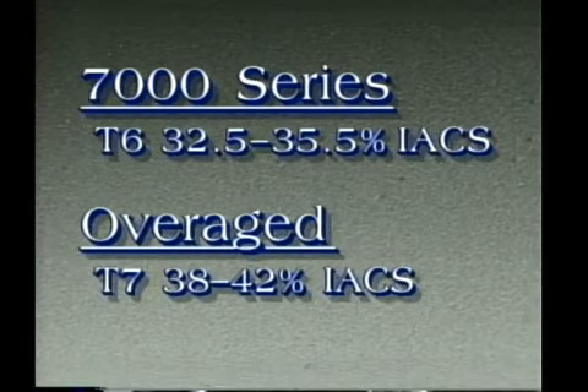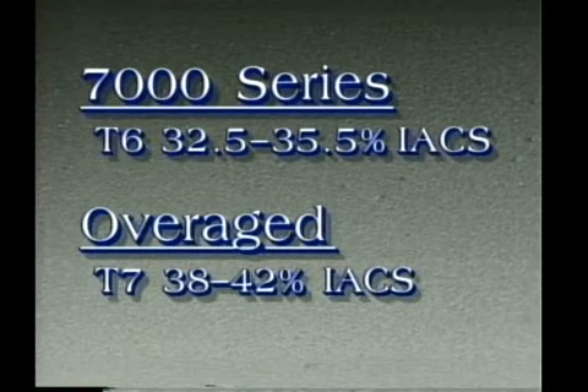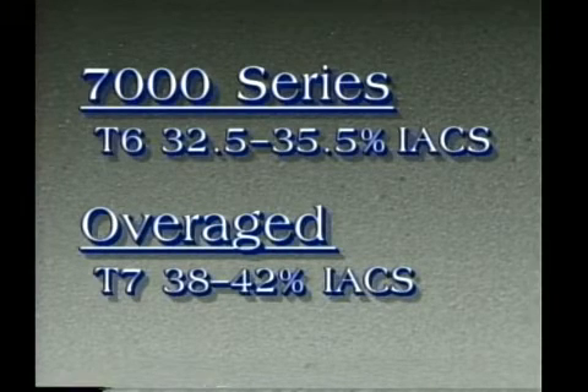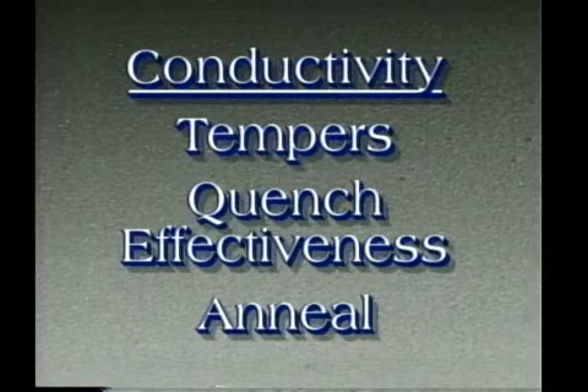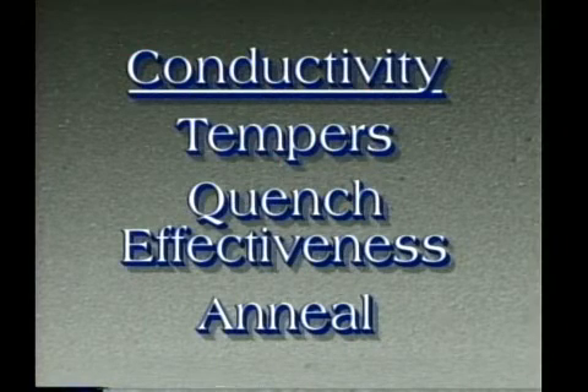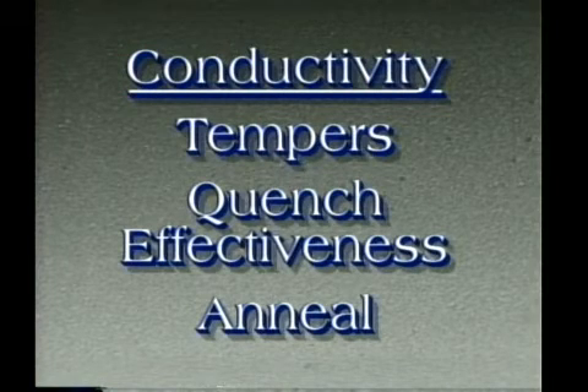The conductivity meter became a valuable tool in the plant, for it could non-destructively verify that a material had been properly overaged. When first used, conductivity testing was only used for this purpose. It soon became evident, however, that the conductivity test had applications beyond its original intended use. It was found that other alloys, such as many 2000 series alloys, showed similar electrical conductivity characteristics as a function of heat treatment. Other applications have proved valuable. The conductivity test can also be used to determine the effectiveness of a quench, and in some instances, determine if an aluminum alloy has been properly annealed.